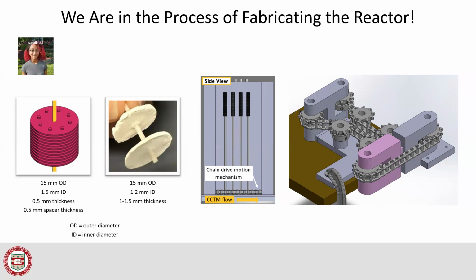So we wanted something that had this high surface area, but we also wanted to pack it fairly densely. So a disc was a pretty natural choice. Believe it or not, what we can do these days is 3D print a mold, and then we can take the material and press it into the mold and form this disc. I think this is amazing. We can make very complicated shapes, they call them form factors. We could turn it into little triangles that stack, or we could make little cubes, like a few cubes of cheese on a toothpick or something. We could do almost anything, because we can 3D print a mold and press it into the mold and the material holds up. So we create this disc, and then we put them on a conveyor belt.